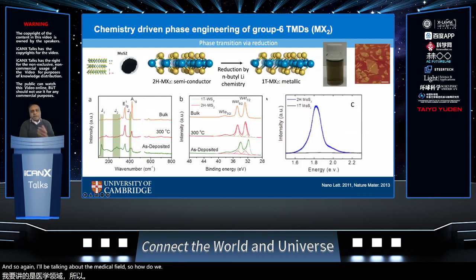So how do we make these materials, and how do we do the phase transformation? The phase transformation is really interesting because it occurs at room temperature and room pressure. This is another interesting aspect of these 2D metallic TMDCs, because we can achieve phase transformation at ambient conditions. We know that to achieve different phases in materials typically requires high pressure or high temperature.